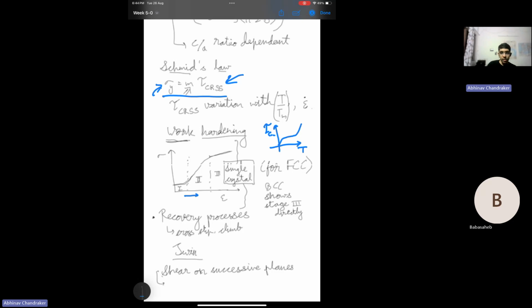You could also see that as if you are doing a uniaxial test on a material, you are giving a constant strain rate. So the strain is increasing constantly with time, but the stress required to cause that strain change is increasing in this manner. So this indicates that the material is getting harder and harder as you are giving more strain to it. In a way, you can say that deforming a material is making it harder, or we can call it work hardening. We can say that work hardening is taking place in the material. And we'll look at this in more detail.